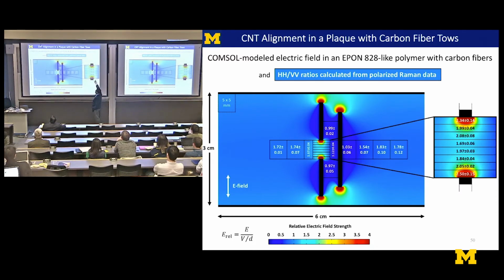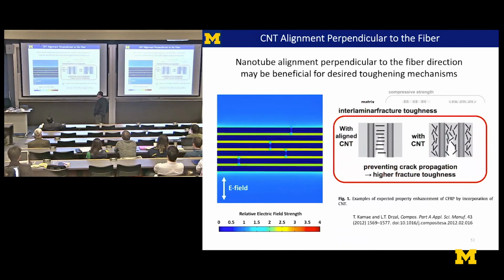And in fact, the Raman spectroscopy is showing the alignment occurring in the direction we want, in the location we want. The issue now is, in order to do the Raman, we're doing it at very dilute levels of the CNTs, so now he's going to be increasing it in the 2 weeks you have before you start your job and get this done. The other thing is, can we get the alignment for load transfer in between the carbon fiber tows?